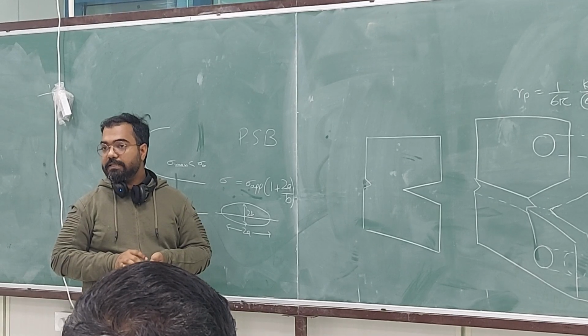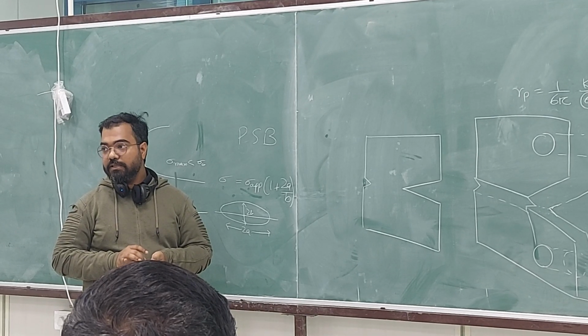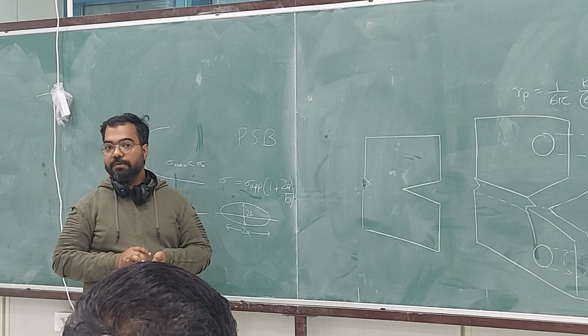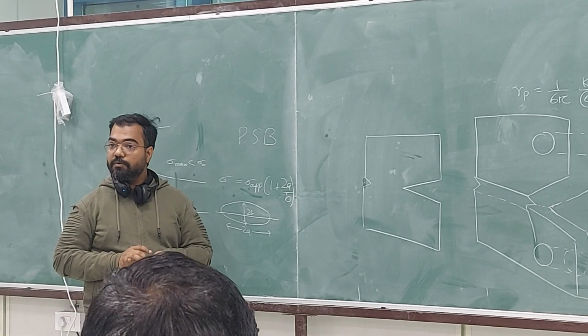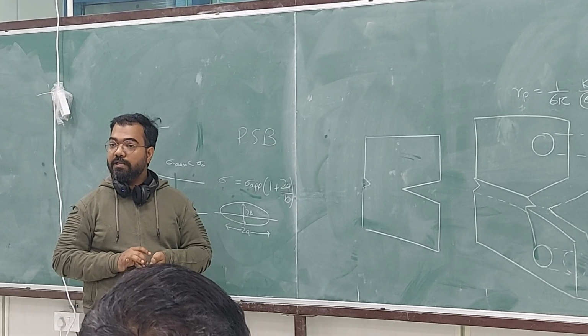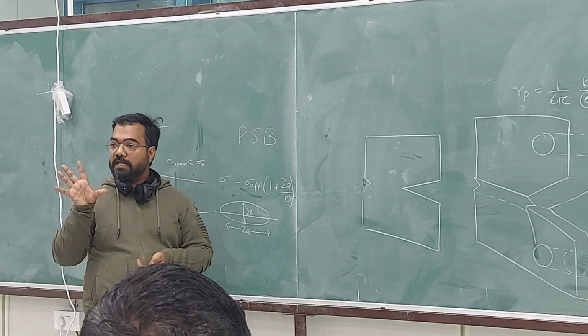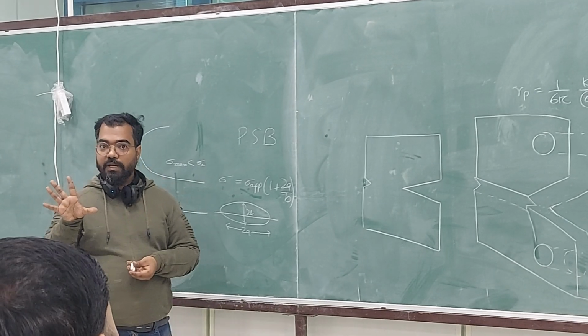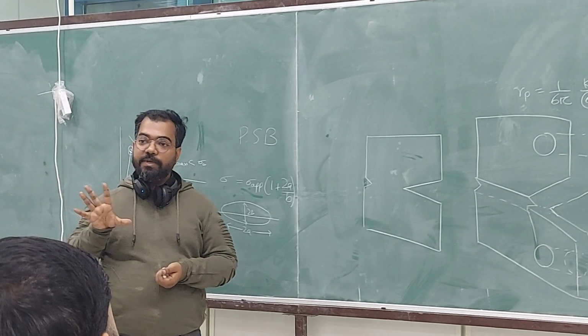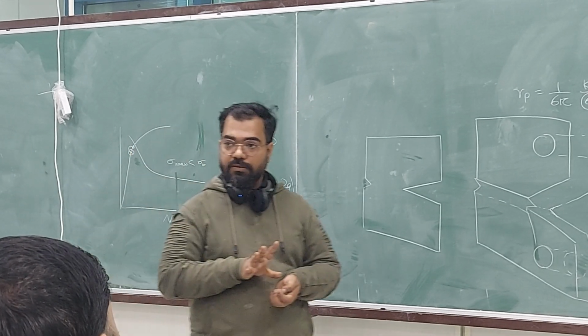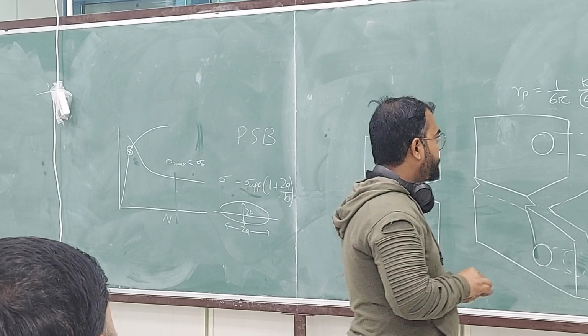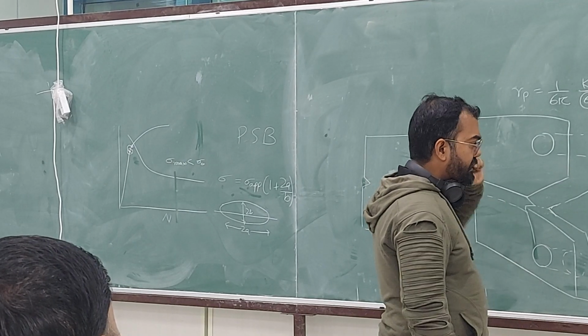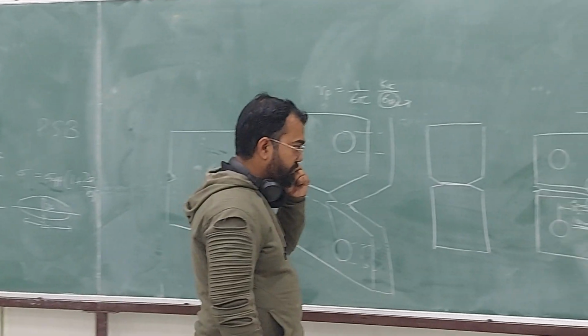So even at stresses lower than yield strength under cyclic loading, people found that dislocations are moving and plastic deformation is happening, not in all the grains, but in some grains. So plastic deformation can happen even below yield strength. Fine, we'll discuss that later when we discuss fatigue.